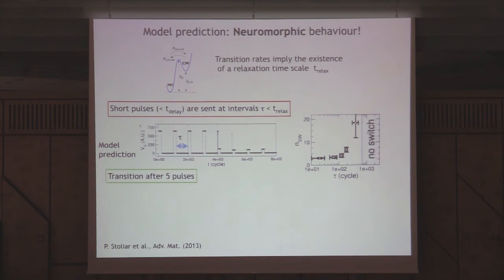On the other hand, if you are beneath this time threshold, you will have a transition, and of course, the shorter the time between the pulses, your damage has less time to get healed, so you can accumulate pulses faster. So the smallest number of pulses will be when the time between pulses goes down to 0. You could do that in the simulation. For this parameter you have 1, 2, 3, 4, and in the 5th pulse, you have a transition. Once you have the transition, the system remains there. It doesn't have enough time to relax back. Every time it wants to come back, you switch it on.